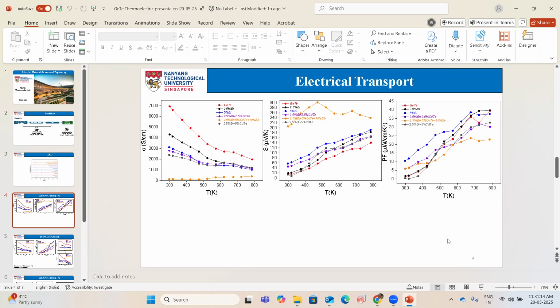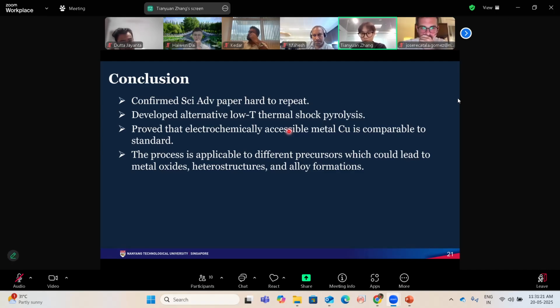And after this, here is our conclusion. First, we confirmed that the Science Advances paper is very hard to repeat because the cellulose is a very big problem. It's very hard to make a thin, uniform, and high coverage layer of cellulose. And in this background, we developed our alternative low temperature thermal shock pyrolysis by just removing the cellulose layer and finding a new low decomposition temperature copper salt as an alternative.